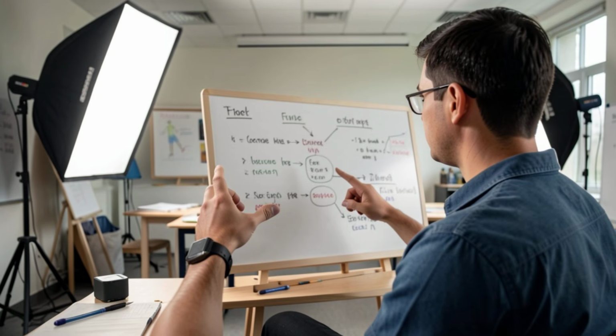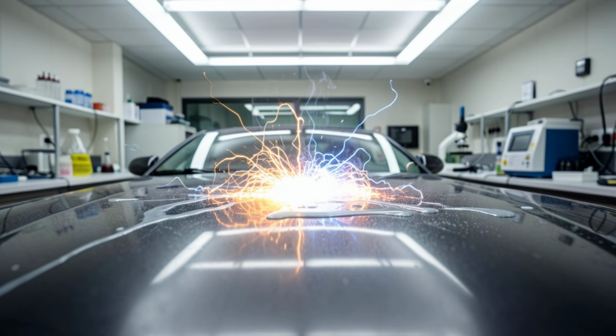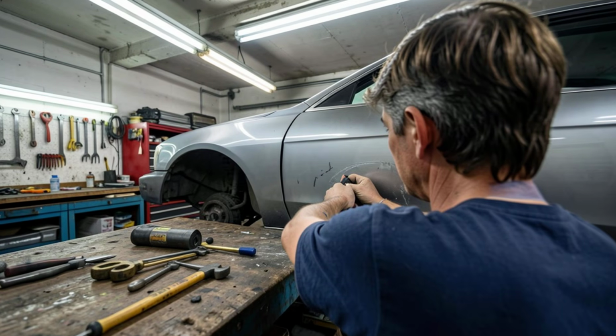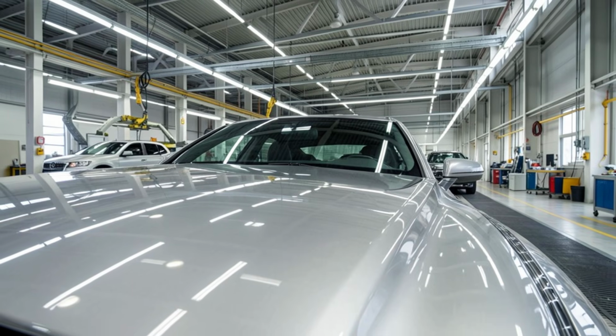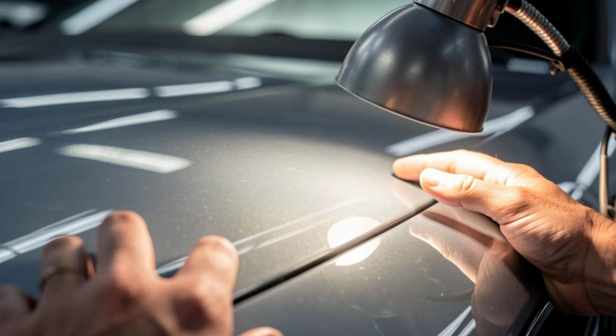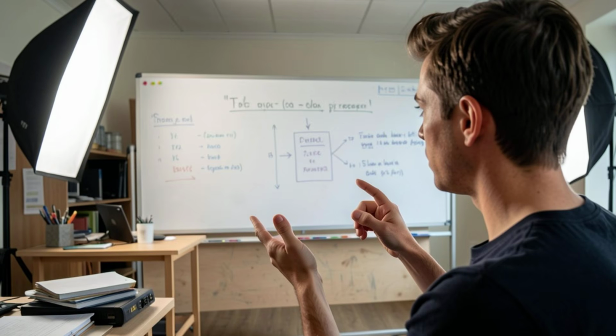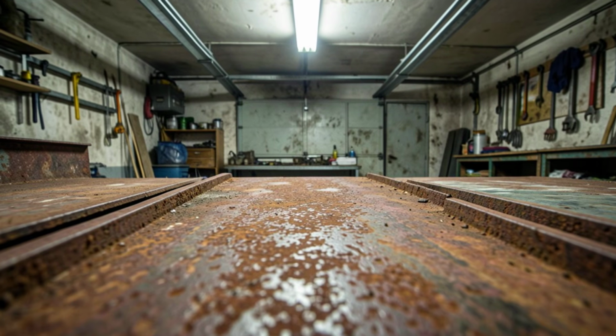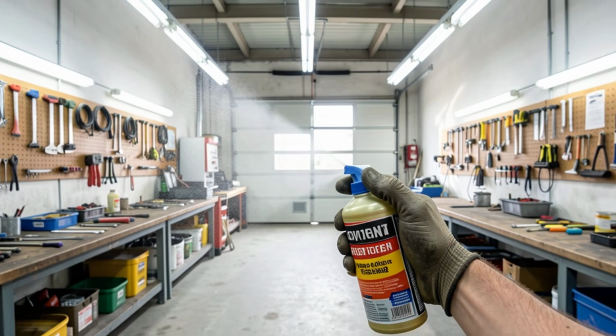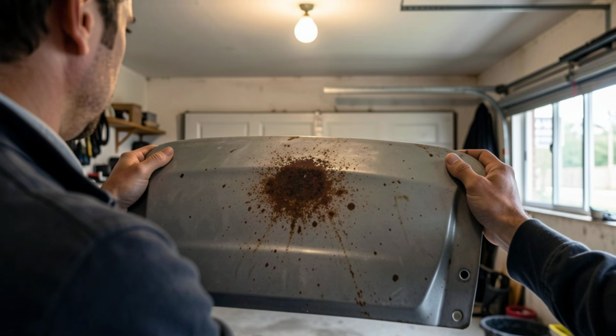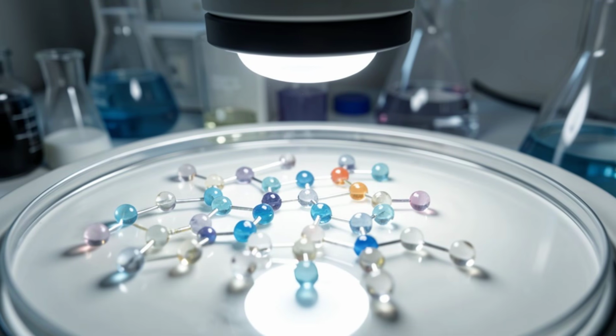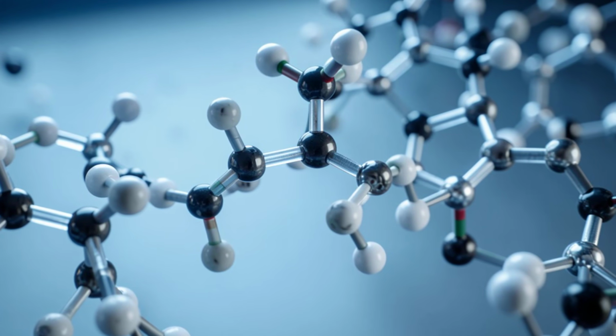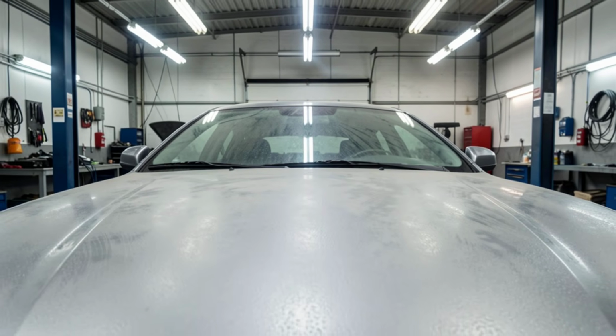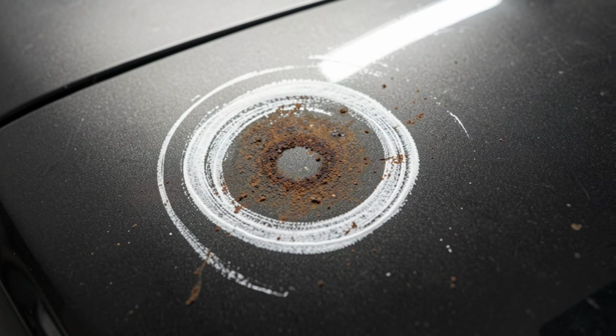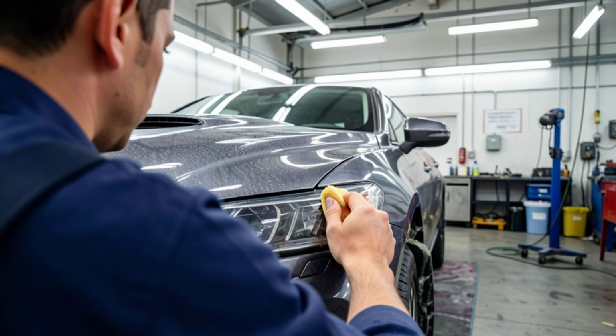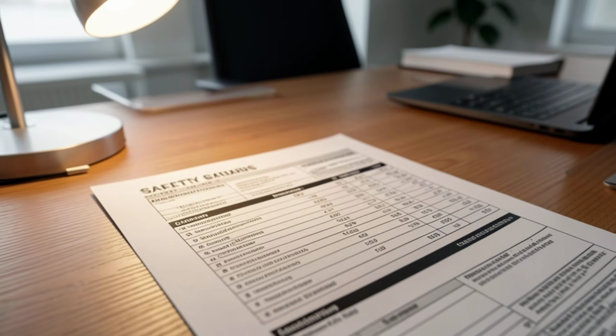More relevant to your car, phosphoric acid at working concentration does not discriminate between iron oxide and the surrounding surface chemistry of automotive paint. The acrylic urethane polymers that make up your clear coat are resistant to very dilute acids, but they are not resistant to the concentration required to dissolve embedded rust quickly. What happens when the overspray or the runoff from a commercial rust remover contacts your clear coat is a phenomenon called acid etching, where the acid molecules begin hydrolyzing the ester linkages in the polymer chains of your clear coat, creating a dull, hazy, permanently compromised surface that scatters light instead of reflecting it cleanly.